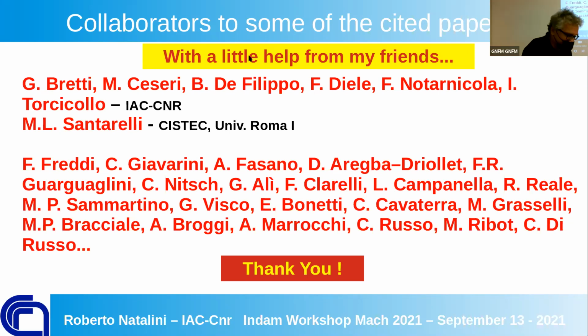It's a nice question, and that's why we conducted a large campaign on the Vittoriano in Rome, where we compared the lab situation with the in situ situation by putting a lot of specimens of different kinds of stones, essentially Carrara marble and Monticino marble, near the monument. We had a big rack for a year and a half, and compared with the same specimens in the lab, made by Bretti and Santarelli, with the Institute of Conservation of Cultural Heritage, the IAC-CNR in Rome.